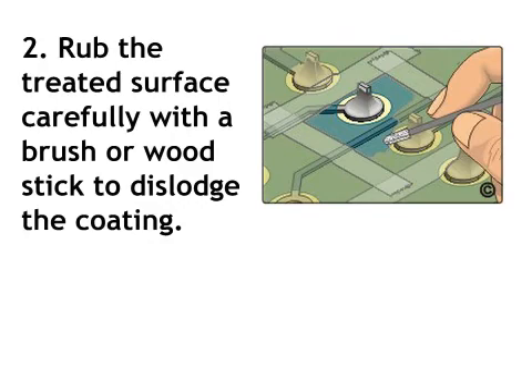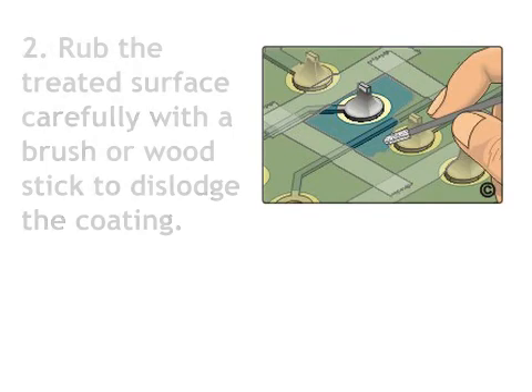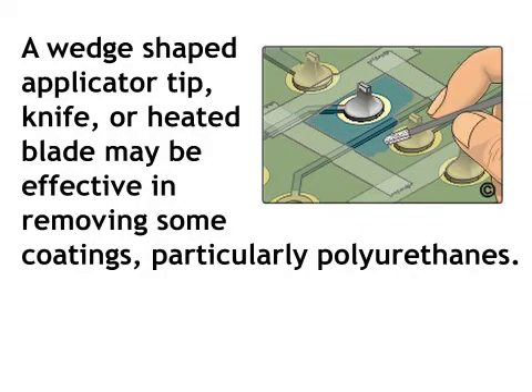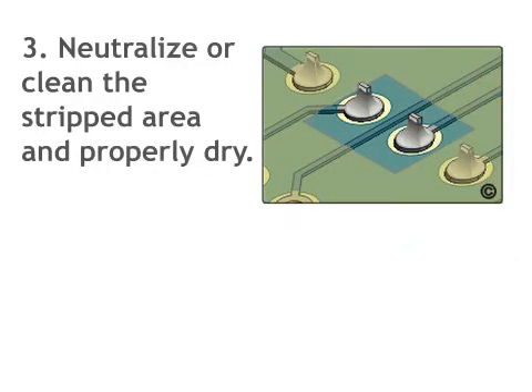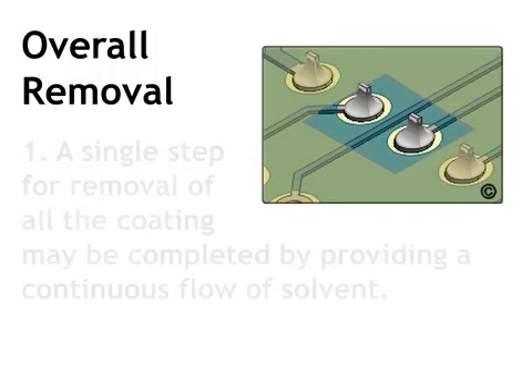Step 2. Rub the treated surface carefully with a brush or wood stick to dislodge the coating. A wedge-shaped applicator tip, knife, or heated blade may be effective in removing some coatings, particularly polyurethanes. Step 3. Neutralize or clean the stripped area and properly dry.